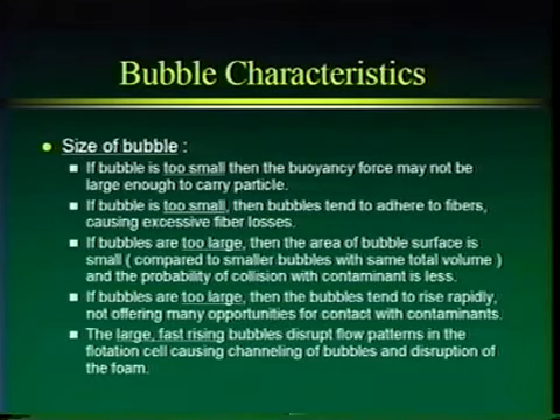If the bubble's too small, the bubbles tend to adhere to fibers. So even though fibers are hydrophilic, bubbles will attach to fibers if they're small enough. And if a lot of little air bubbles attach to fibers, then the fibers will be floated out. A dissolved air flotation cell works with very, very small bubbles that attach to almost all solids in the system, and that's an example of why if bubbles are too small, they'll attach to fibers.